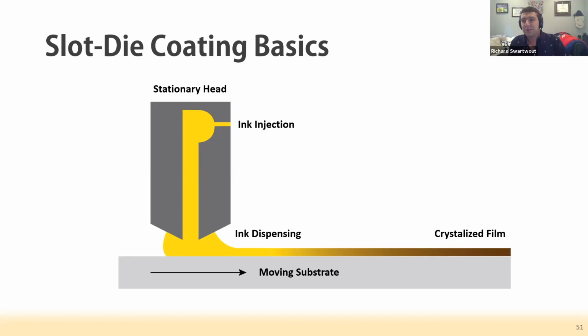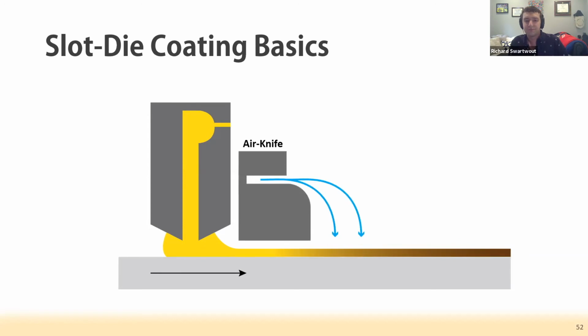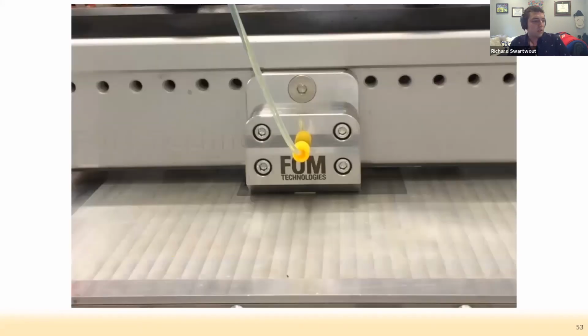Like I said, drying can be a little bit uncontrolled. And so to improve uniformity, you can add an air knife. This, of course, is also along the same linearity of the moving substrate. But it promotes active drying and then gets you a much more uniform crystallized film.